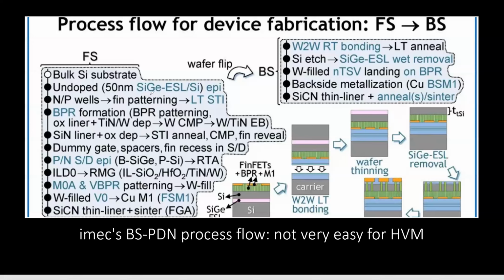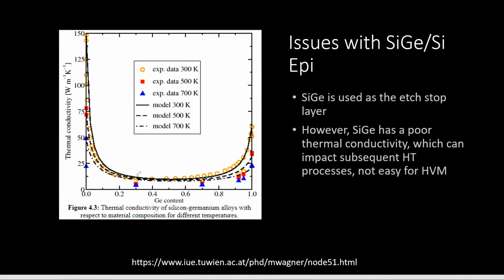It doesn't work that way. Then you cannot put 50 nanometers, probably only 3 or 4 nanometers. So 30%, I would think, is a good number to have. But if you look at 30% here, your thermal conductivity dropped from 150 to 15, 10 times smaller.